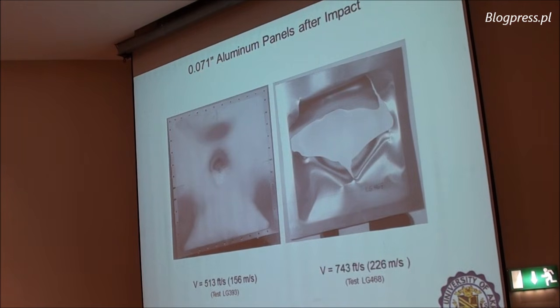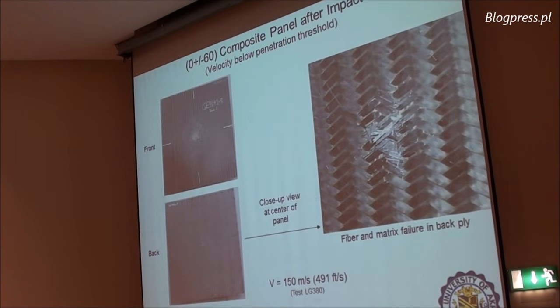And you can see on the left the deformation of the aluminum before it fails, a little bit higher velocity, and it failed, and the failure is definitely very detrimental. Now, the composite offers more crack resistance, so when you have a failure, you have local fiber breakage. Even if we have the application of this material, you can see it is more elastic, it is gentle, it behaves like a spring, and